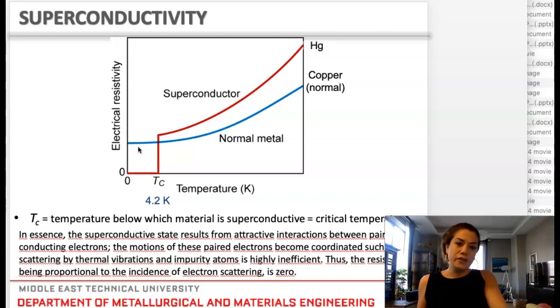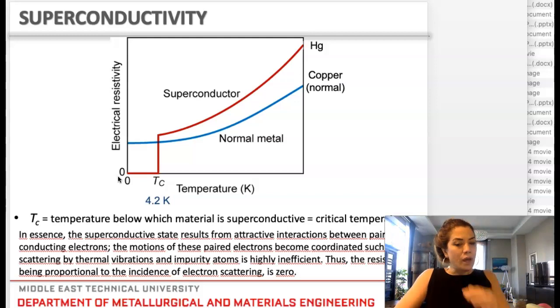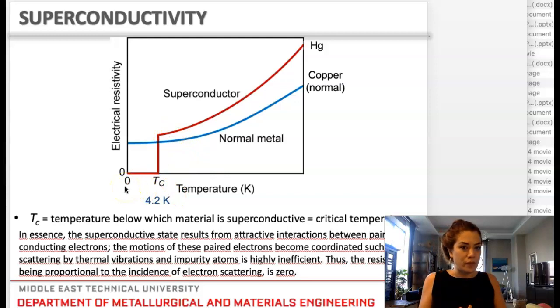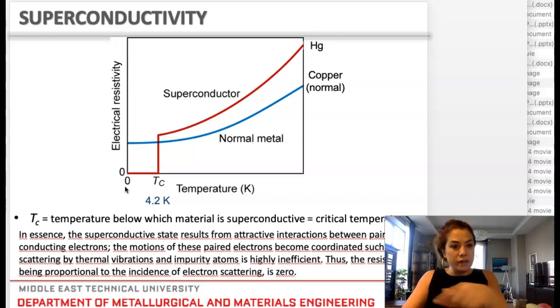But in the case of a superconductor, for example mercury, up until a certain temperature the resistivity drops, but at that critical temperature, which is 4.2 Kelvin for mercury, absolute zero is 0 Kelvin, you know? So this is like 4 degrees Kelvin above absolute zero. The mercury acts like there is no resistivity in the material at all. It drops to 0 all of a sudden after a certain temperature. So if I was to make a loop out of this mercury, since there is no resistivity, the current will flow for an infinite amount of time, because there is no loss of energy, right? So the loop continues until infinity.